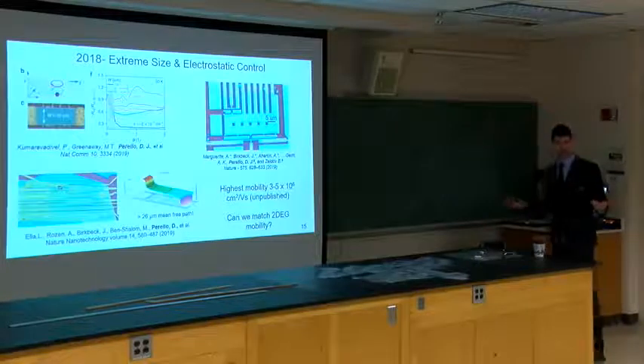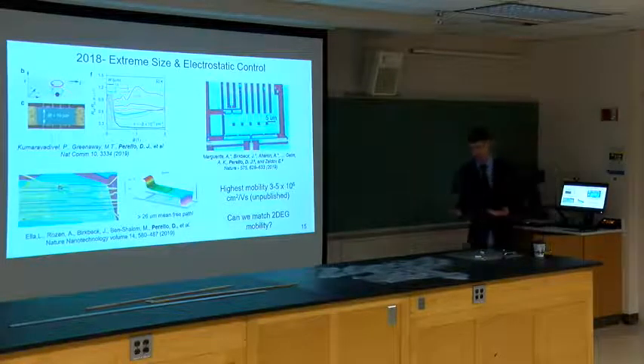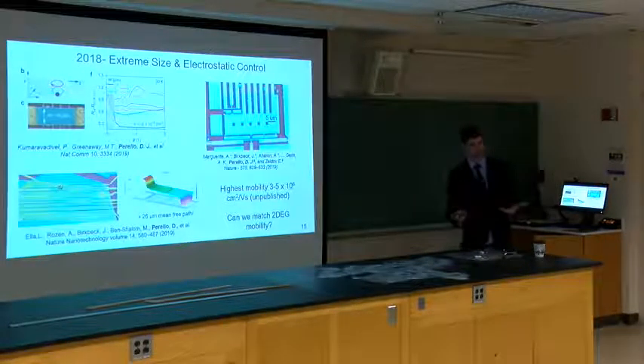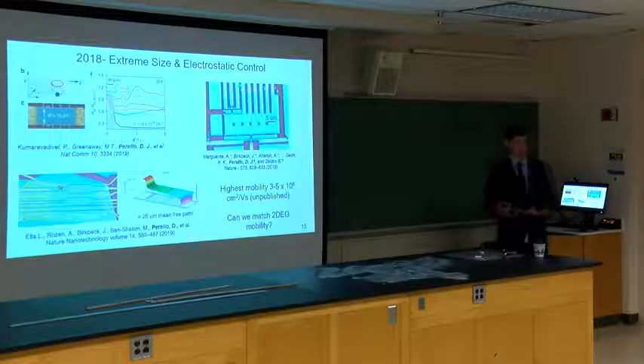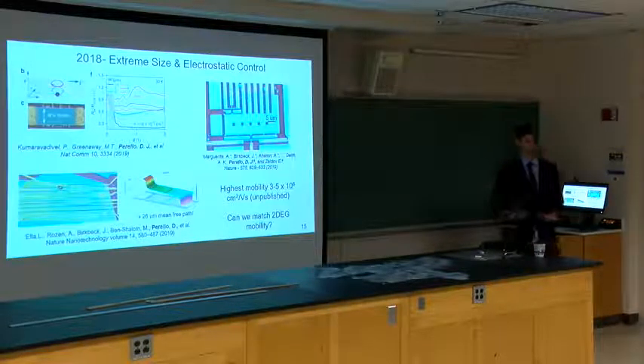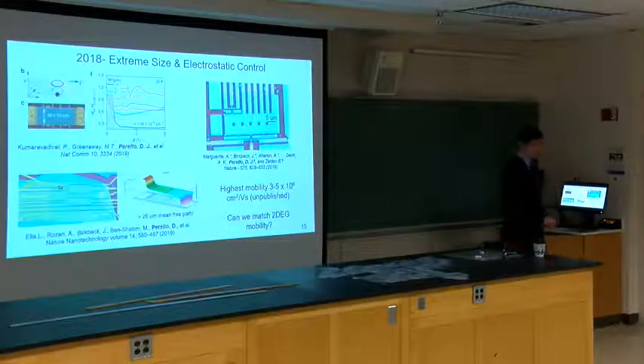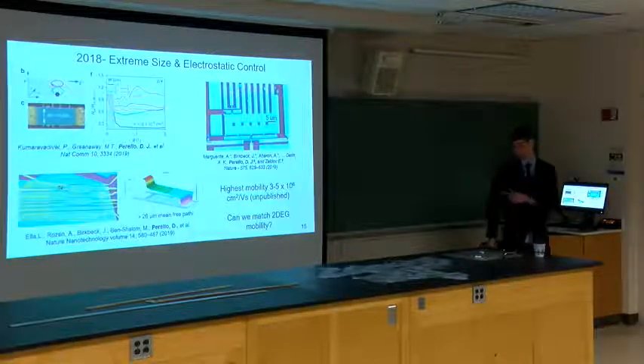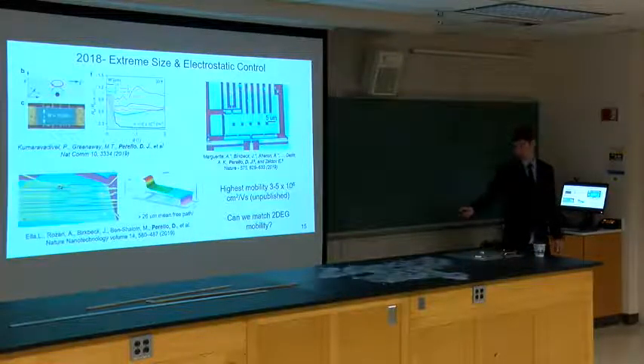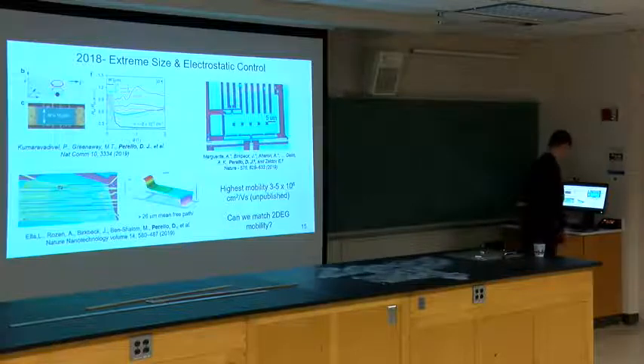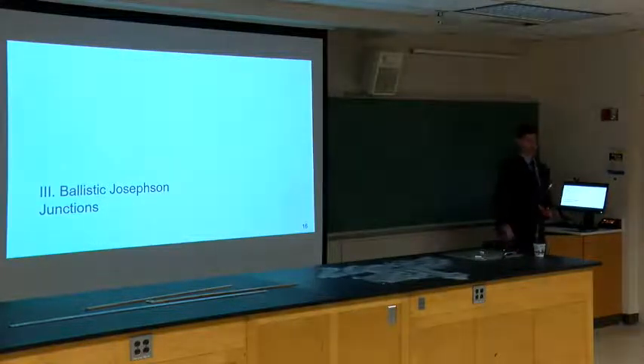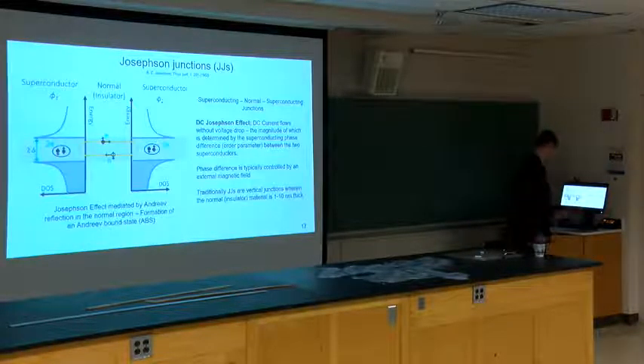Okay, we can have mean-free paths that are maybe 100 microns, but the typical response from the two-dimensional electron gas community is, well, how high is your mobility? And no, we can't beat them yet. We might have a chance, though. We haven't measured these devices at low density, so we might have already actually beaten them, but we didn't look for that in those samples.